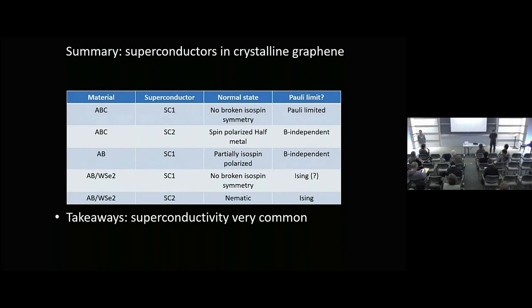Hi, so monolayer graphene also has saddle points, so what's the story there? The story is that those are at like 10 to the 15 electrons per square centimeter, and if you know how to do that, you should definitely do it. It'll be a room temperature superconductor. Meaning you can't tune the density? You can't tune the density.